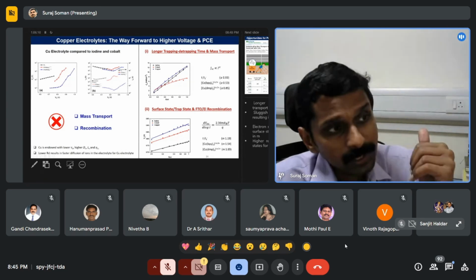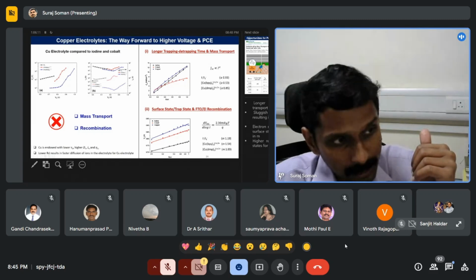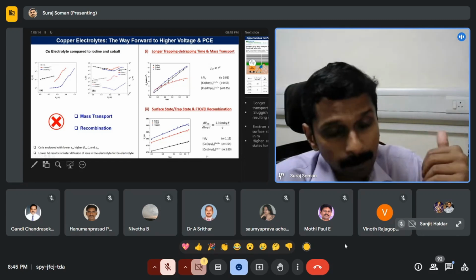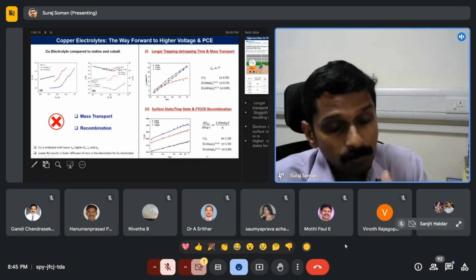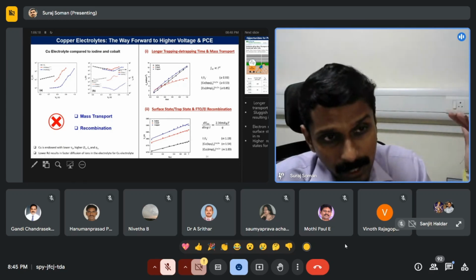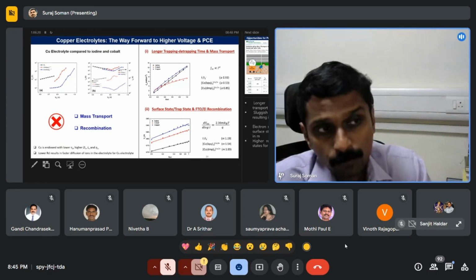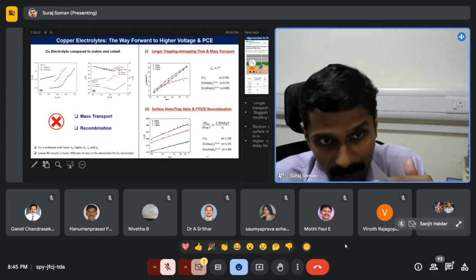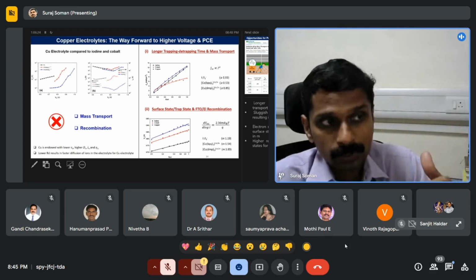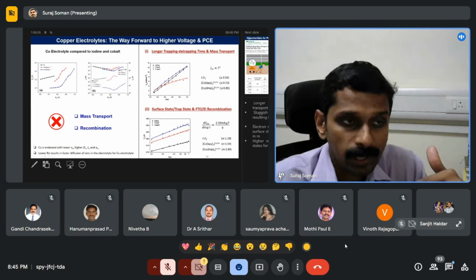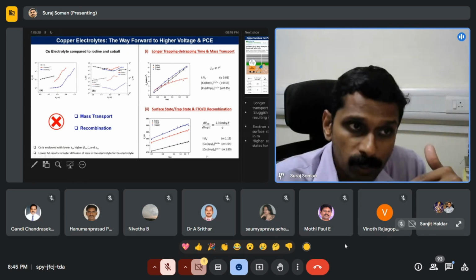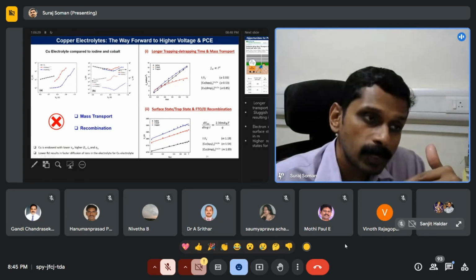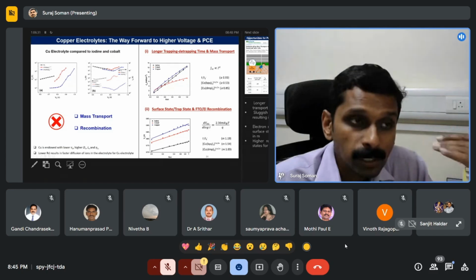What we have seen is that when you use the copper-based electrolyte, there is a negative shift in the conduction band. When you have a negatively shifted conduction band, your driving force for recombination is automatically high, so your lifetime should be less. But the copper, even with more driving force for recombination, maintained a lifetime similar to iodine and cobalt.